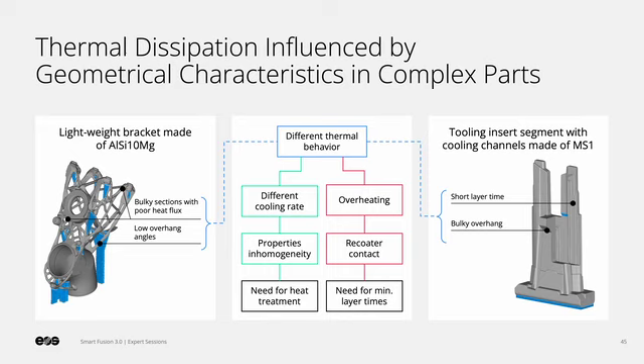This means we will have a different cooling rate in different positions of this part. As previously mentioned, changes in cooling rates affect solidification conditions and directly impact microstructural properties. Therefore, different cooling rates lead to inhomogeneity in properties. Often in industries, to tackle this problem, they use post-processing steps like heat treatment for properties homogenization. Using heat treatment will increase cost per part and also manufacturing time.